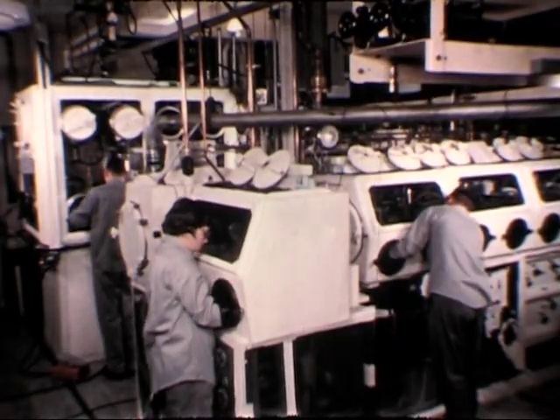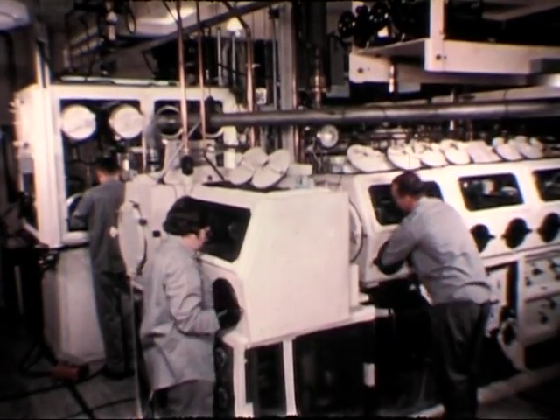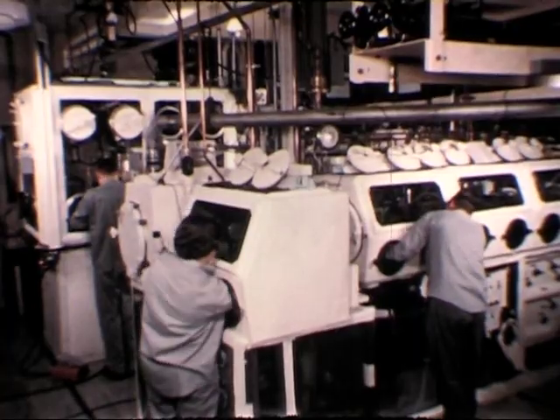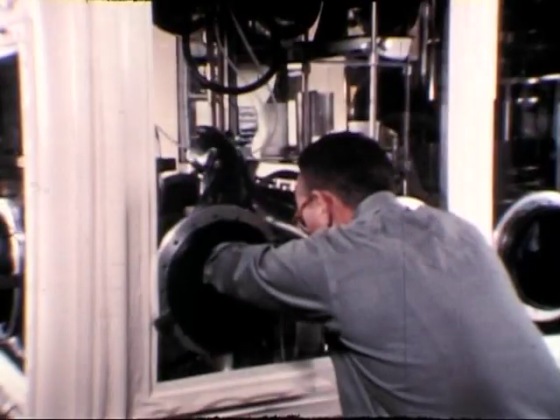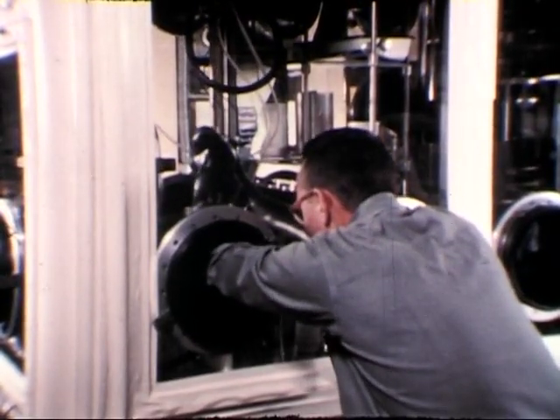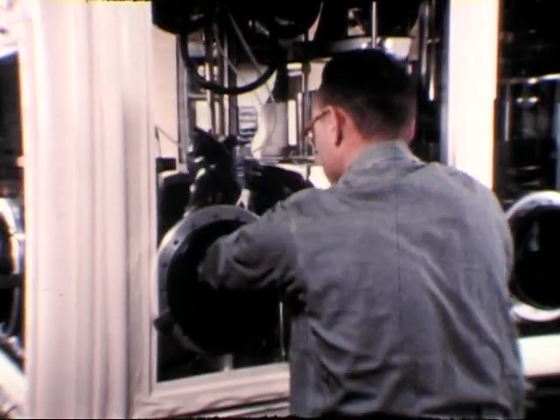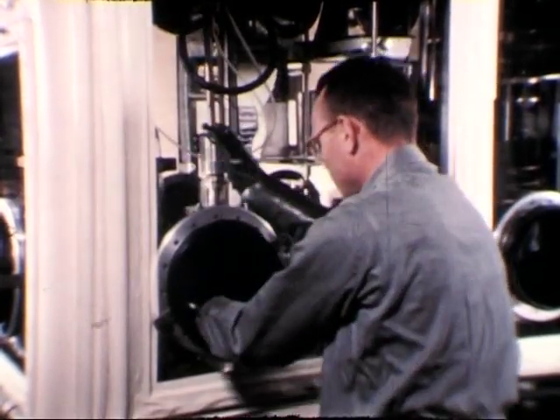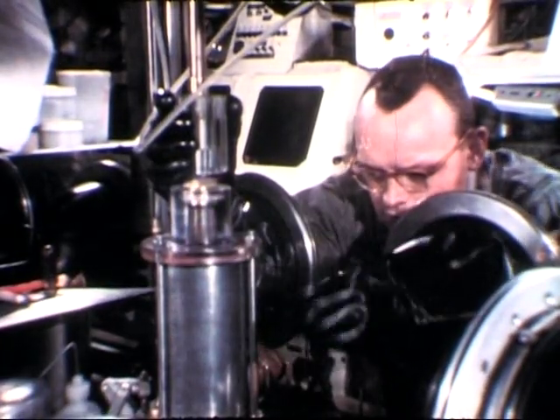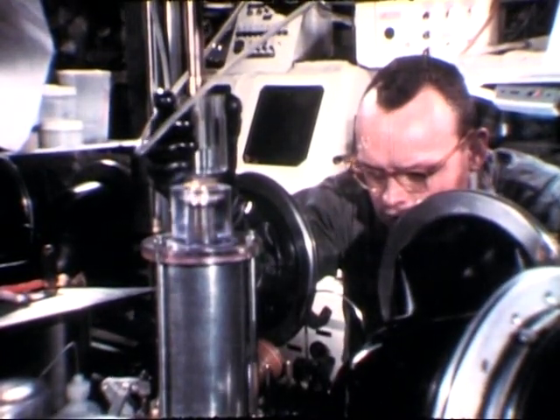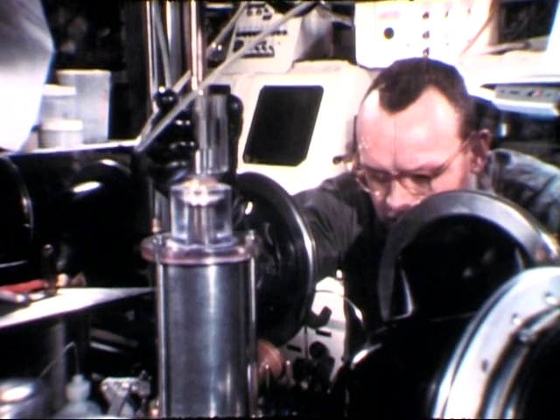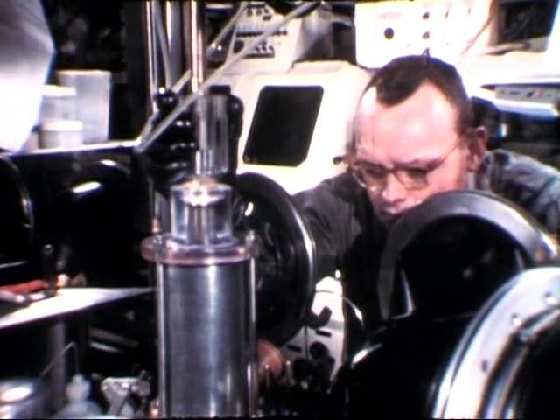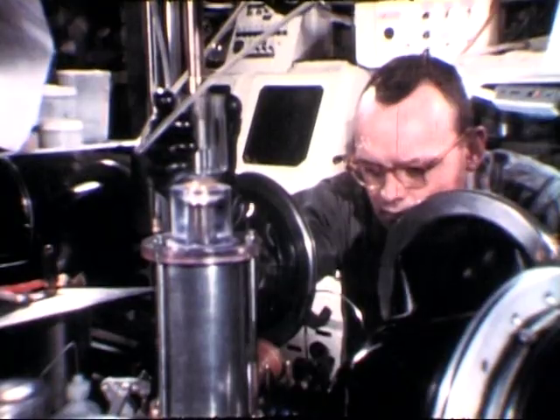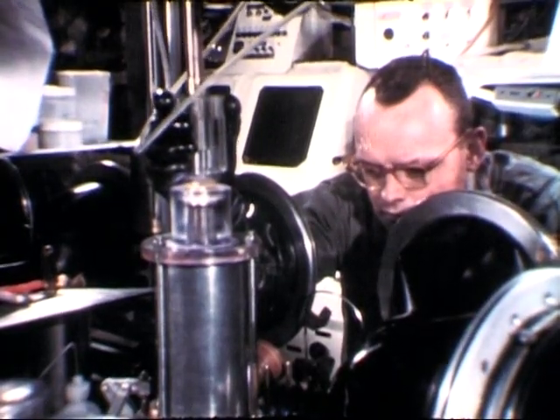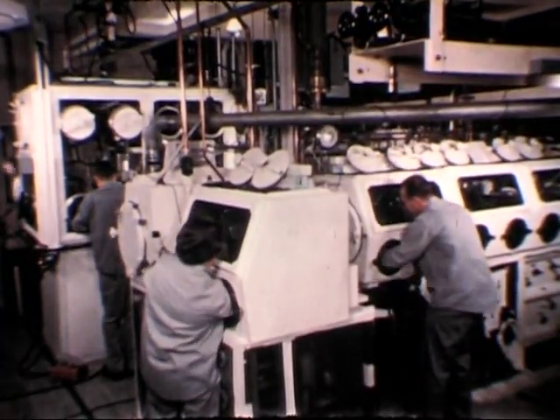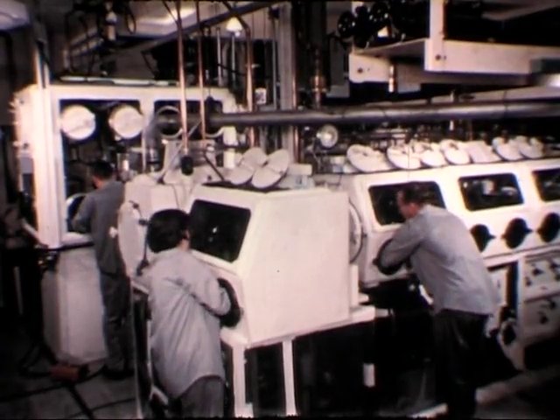Because the pyrometallurgical process permits control of residual fission products, varying concentrations of 3 to 15 weight% fission product elements have been included in the alloy. The alloy tested is of 70 weight% uranium, 20% plutonium, and 10% fission product elements. Irradiation stability is good, and thermal conductivity is slightly less than uranium. This alloy shows excellent compatibility, even under irradiation with the sodium coolant.